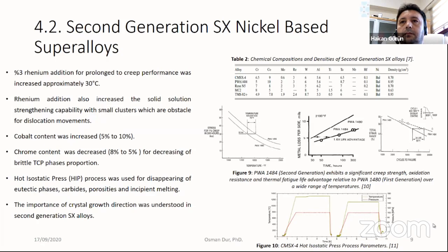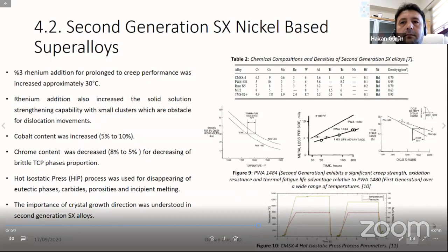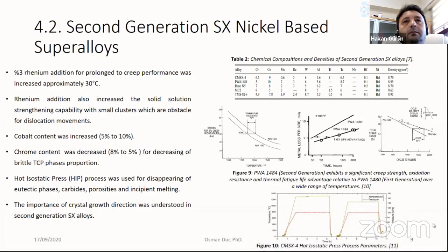Hot isostatic pressing was used for the first time for eliminating porosities, carbides, and incipient melting. You can see in figure 10 the hot isostatic press example. This application was part of production of the famous second generation CMSX-4. The importance of crystal growth direction was understood in second generation alloys.